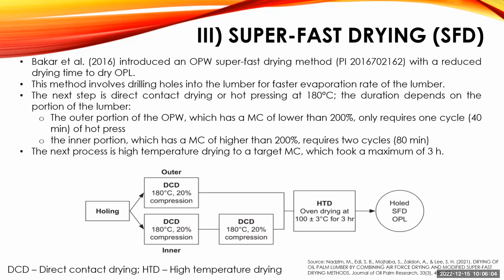After direct contact drying, the oil palm lumber is put in an oven for high temperature drying at 100 degrees Celsius for 3 hours. That's the whole process. But this process is unfavorable because we need to use the holing process on the oil palm lumber.